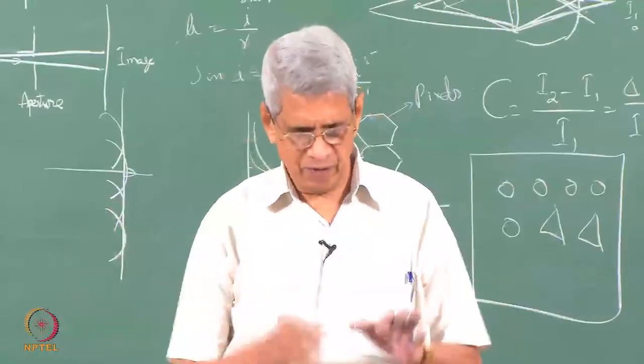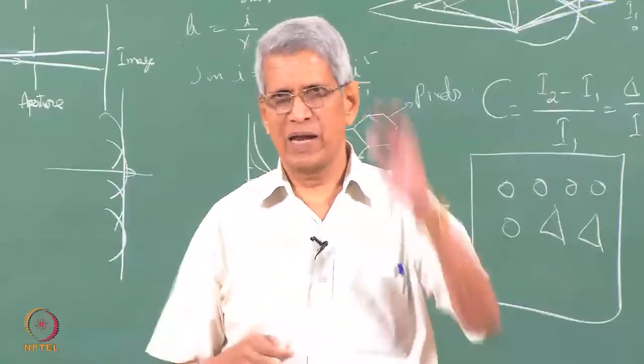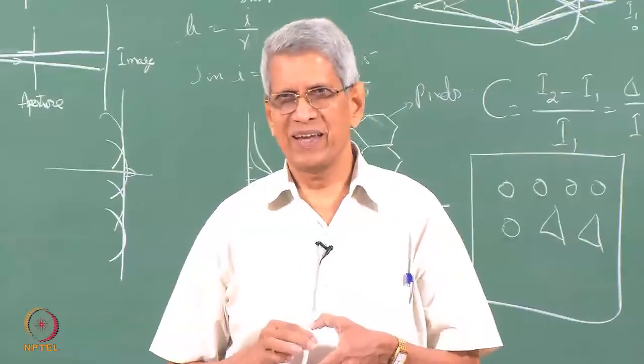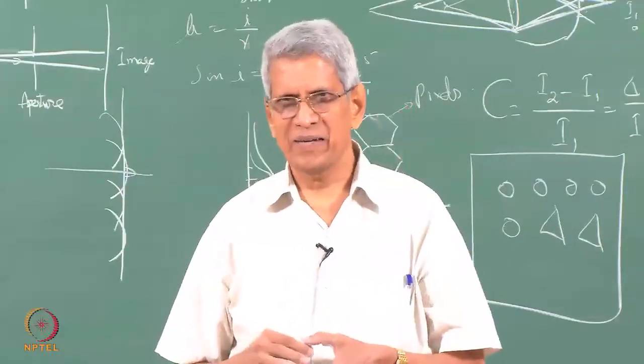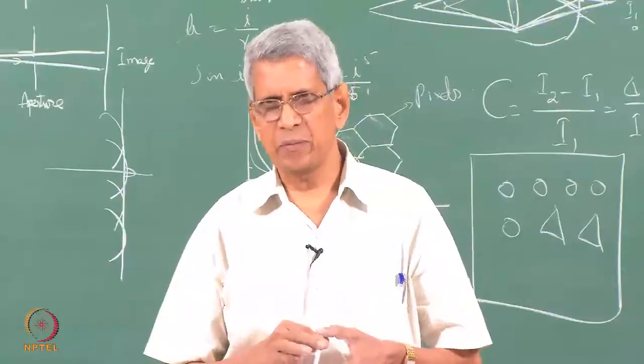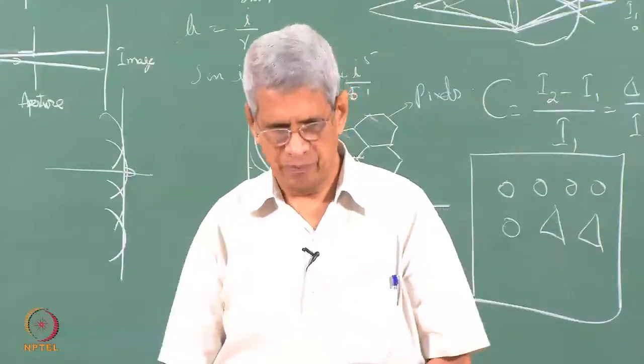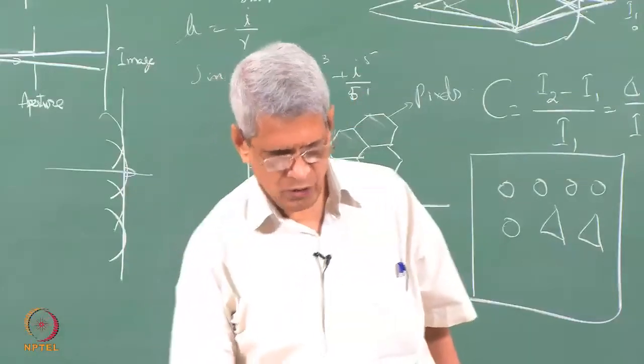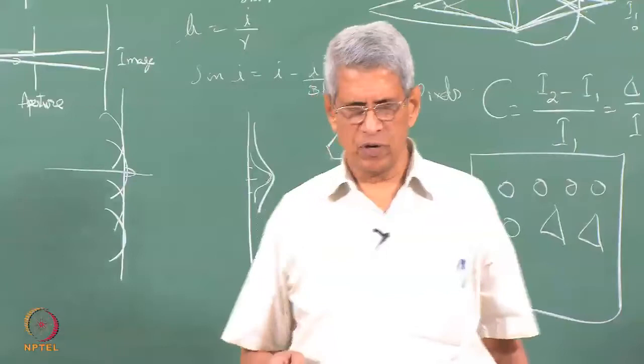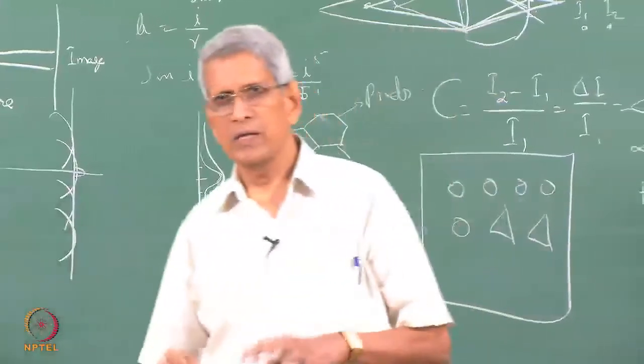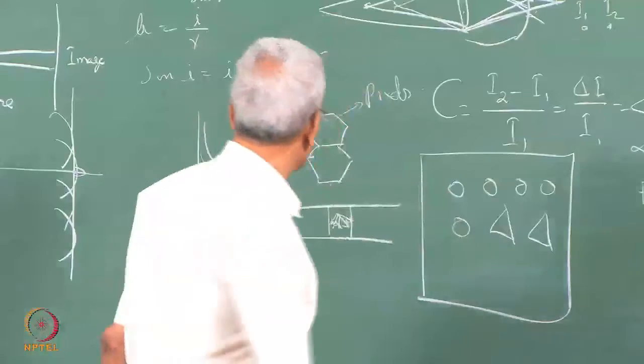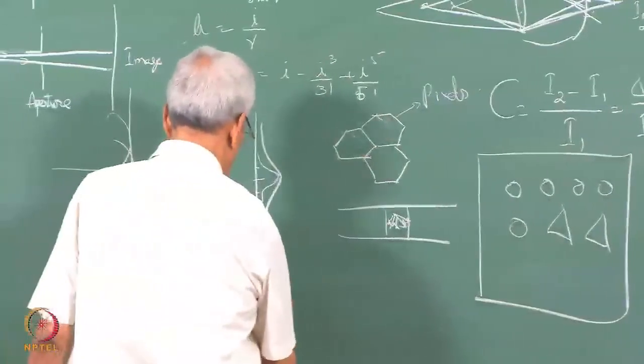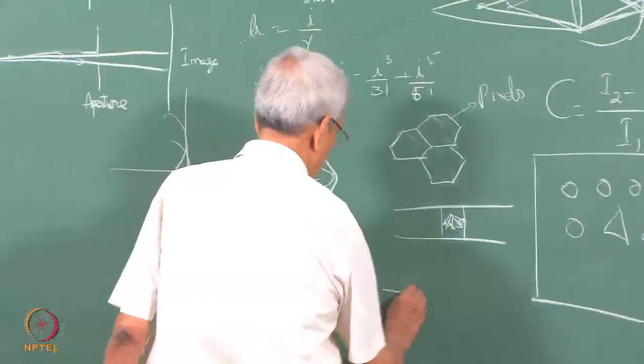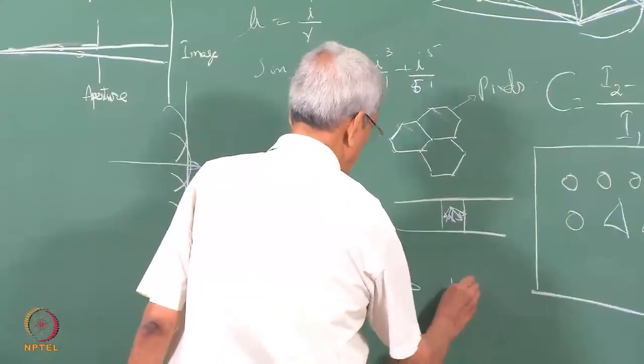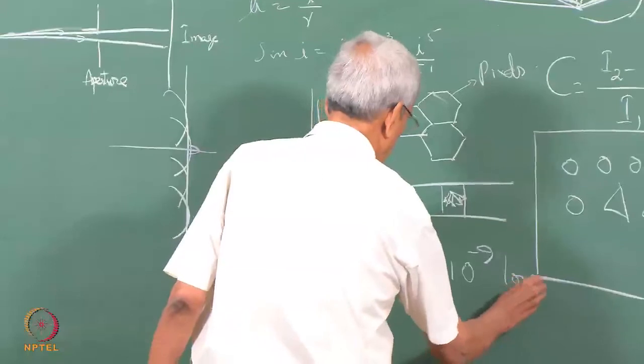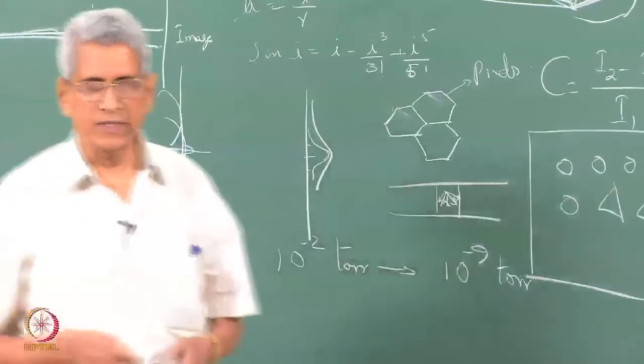Another thing which you should remember is that we are talking about an electron microscope, an electron beam which we have to use. That means the electron strongly interacts with matter, it can get scattered and its energy can be lost. So we require a very high vacuum. Vacuum could be obtained using a rotary pump, diffusion pump, turbomolecular pump, getter ion pump, cryosorption pump. There are various types of pumps which give vacuum from around 10 to the power of minus 2 torr to about 10 to the power of minus 9 torr.